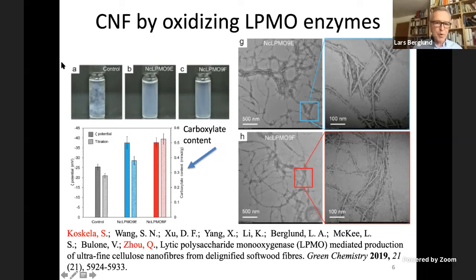If you look in the upper left corner here, you see the control. And these are the two fibril materials made using the LPMO enzyme. And if we look at carboxylate content, you see it's substantially higher than the reference. The reference gets the carboxyls from the hemicelluloses, but they're able to increase the carboxyl content, and this is why they see such fine fibrils.